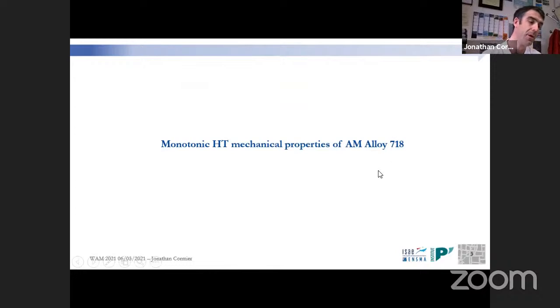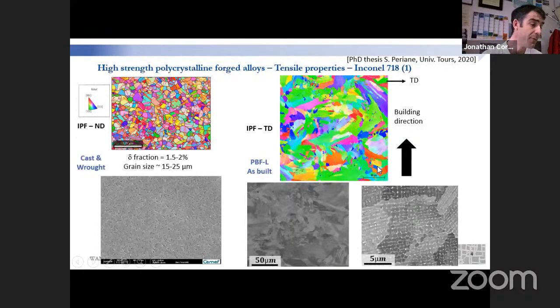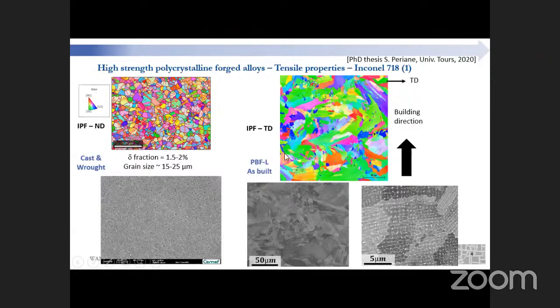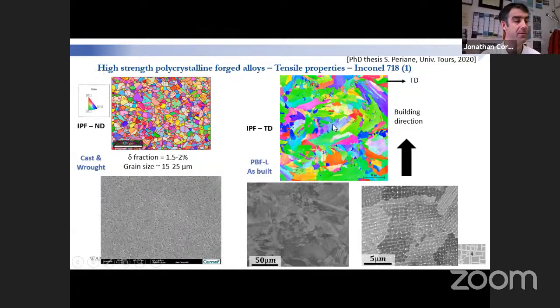This alloy makes up nearly 50% of the weight of an engine. And first of all, I'd like to make a comparison between state-of-the-art materials, so conventionally forged alloy, a cast and wrought with a fine grain microstructure ranging from 15 to 25 microns, with a given level of strengthening provided by intermetallic precipitates, so gamma prime, gamma double prime mainly, and powder bed fusion laser alloy 718, where you can see a comparison of the typical microstructure. So typical equiaxed microstructure with several twin boundaries here, while for the as-built SLM material, you have this kind of typical microstructure, and at a lower scale, we can recognize a cellular type microstructure.